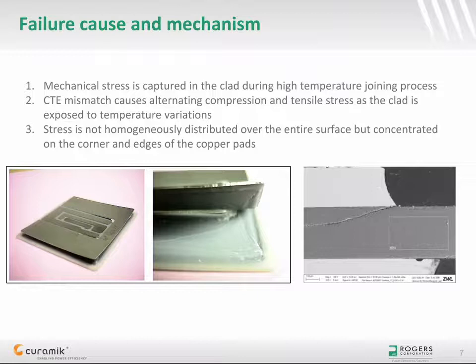Metal and ceramic have different coefficients of thermal expansion, meaning that these two materials do not expand and shrink at the same pace when they are exposed to temperature variations. As they are joined at very high temperature, up to typically 800 degrees C for AMB or 1060 degrees C for DBC substrates, mechanical stress will be captured in the clad of material already during the joining process.